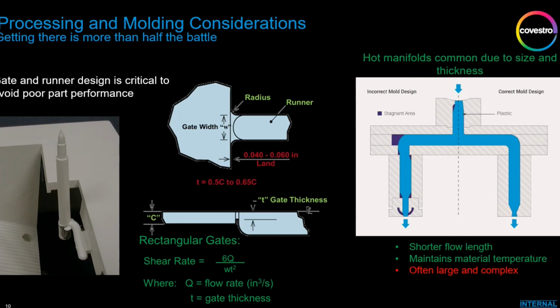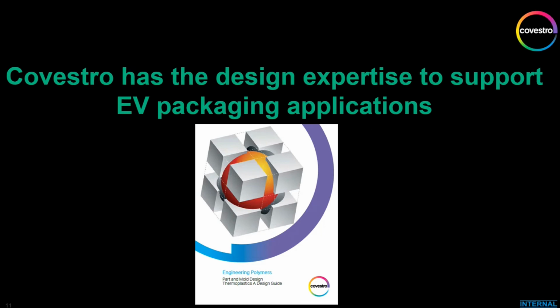So we also need to consider the gate and delivery system. Again, the gate and runner system can cause many problems. It can result in high shear stress if we don't design it properly, or high shear rates in the gate, which can cause degradation of the material, cause it to start to break down. In addition to that, if say a manifold system like is shown here on the right is not properly designed or is not sized properly, we can have that long residence time, or the material sitting in a very hot condition for too long, breaking down, losing properties, and ending up with a part that's not as strong as we need it to be. So even something as simple as how you get the material into the mold needs to be considered early and upfront.